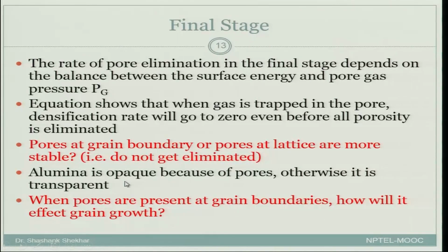And pores have a very strong role to play. For example, alumina is opaque. You have seen it is very opaque. It is almost white colored. It is mainly because of pores. Otherwise, alumina, which is Al2O3, is transparent.